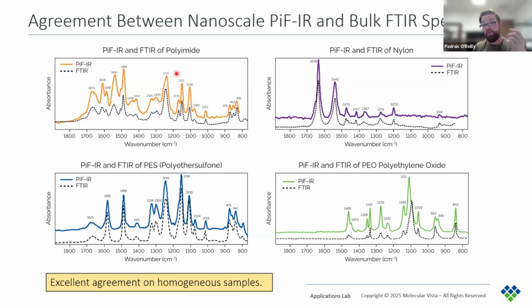So there's excellent agreement between the PIF-IR spectra, which is the term we use for our spectra, and FTIR spectra. You can see here the solid spectra are PIF-IR spectra and the dashed spectra are FTIR. And you can see all the peak positions and ratios match up. So this means that we can use the vast FTIR spectra databases that already exist and have existed for decades. We can use this to identify compounds using our PIF-IR spectra.